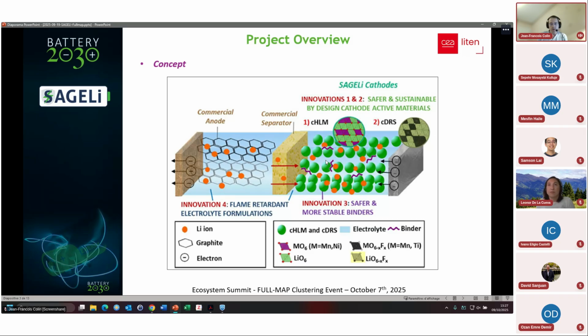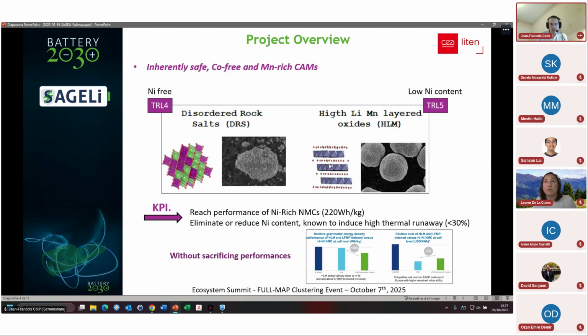In terms of cathode, we are moving away from the cobalt metal and also from nickel. We will develop 2 generations of material with high lithium content but also high manganese content, as manganese is often believed to stabilize the thermal behavior of the material. We will go from 20% nickel in the layered oxide to 0% nickel in the disordered rock salt. The idea is to improve safety but also not sacrifice performance. These materials should at the end be able to perform better than LFP.